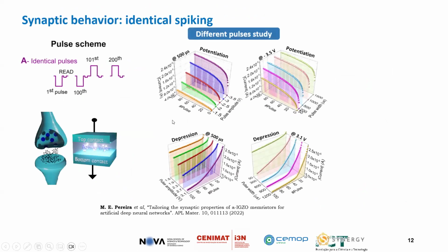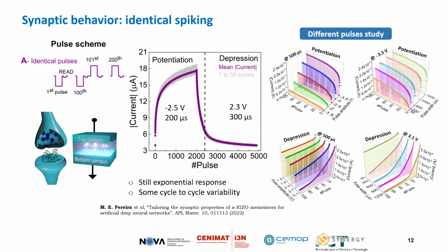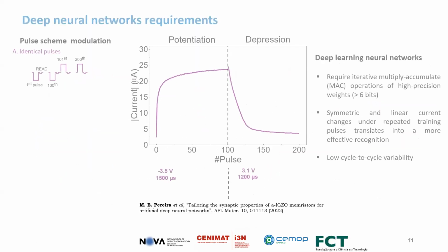In this regard, we are looking at our IGZO device, IGZO resistive switching as an active layer here, and molybdenum top and bottom contacts. If we use identical pulses here for potentiation and depression, we see that we have this exponential change. We change the amplitude of the voltage, as you can see in this figure, and also the time, like 500 microseconds, which is the time of the pulses. This is the real scenario: potentiation and depression, exponentially. However, the device-to-device and cycle-to-cycle variation, over 50 cycles, is very, very low, but it's still exponential. So we would like to tune or engineer it.